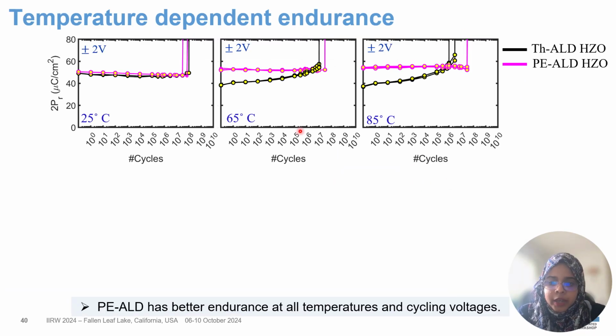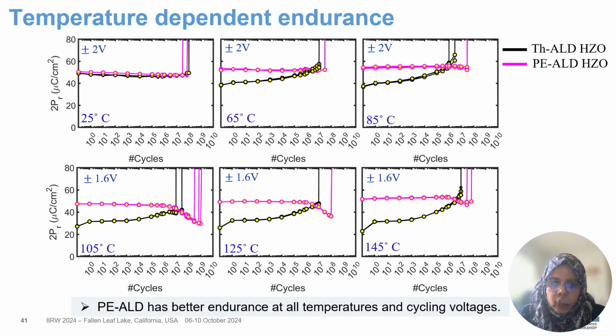Next, we have done the endurance test at multiple voltages as well. Earlier I was showing the endurance test done at 1.8 volt. We have also done bipolar cycling and polarization measurement at 2 volt. What's interesting here is that you can see at 25 degrees Celsius for 2 volt application, the endurance was similar, but the changes come when we go to higher temperature. At higher temperature, the plasma device is having better endurance compared to the thermal one. The same trend is seen in 1.6 volt measurements as well, that we are having better endurance in our plasma device compared to our thermal ALD device.